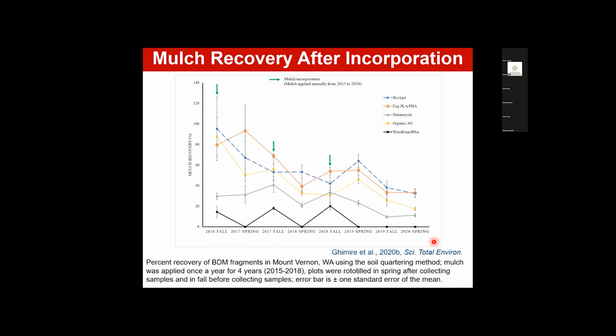There were 4 episodes of annual mulch incorporation and tillage starting in 2015, and those are represented by the green arrows. And what we see here, we have several different biodegradable plastic mulch materials. And the key takeaway is that even with annual tillage and incorporation of these biodegradable plastic mulches, the mulch recovery is decreasing over time. In fact, by the end of this study period, only about 10 to 30% remained in terms of visible fragments. So again, what it shows is that the laboratory standards are useful. They don't necessarily mirror what we see in a field environment, and it is highly influenced by thermal temperature or thermal time based on the work previously published, but they are degrading over time as shown in this study.